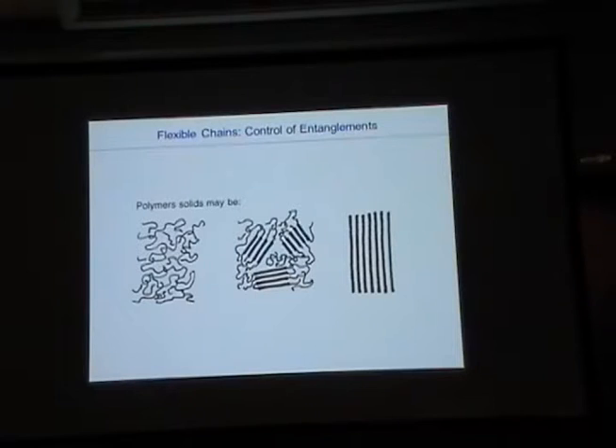So therefore, with exactly the same material, person A in London can get completely different microstructure than, let's say, person B in California, simply depending on the molecular weight of the material and the dilution. We can get amorphous materials, we can get fully chain extended materials, when we have essentially no entanglements left, or anything in between.